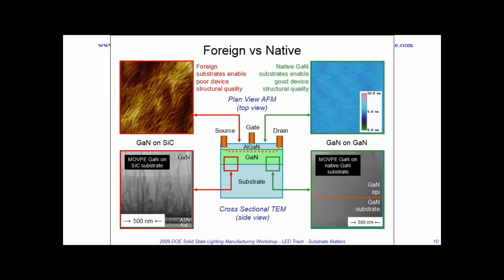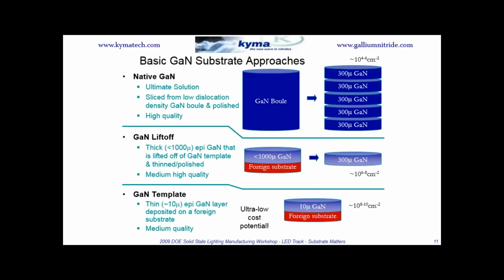And there are some, like almost all the blue and green and white LEDs in the world. But aside from those, all the gallium arsenide, indium phosphide, silicon carbide power devices are all homoepitaxial. So we're always pushing to get the substrates developed if Mother Nature allows us to. And so, unfortunately, it's difficult to grow GaN. That one slide I showed, that a lot of the wide band gaps, you can't grow them from melt. Although there are liquid phase techniques being used, and I'll go through some of those.